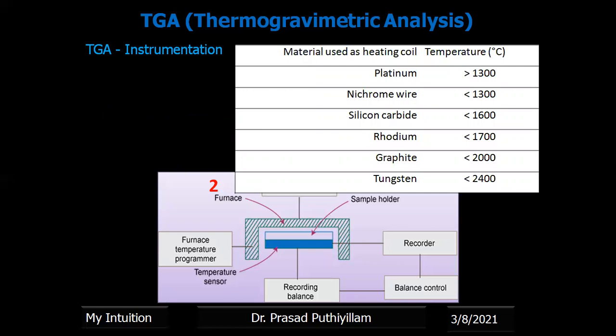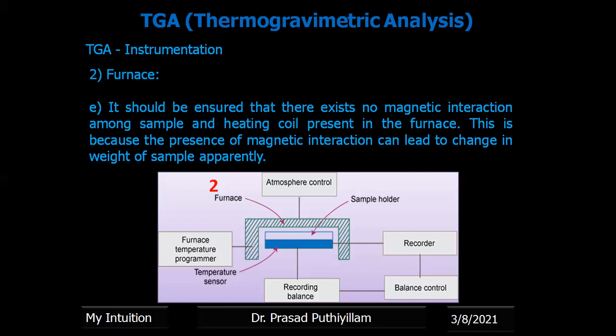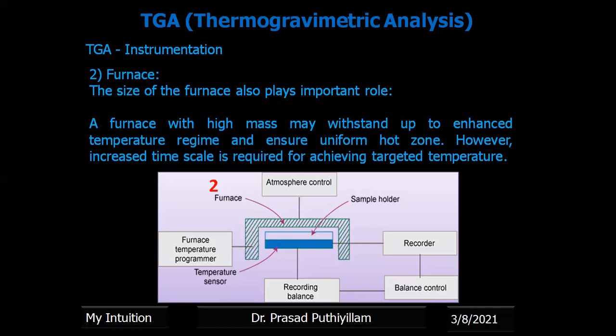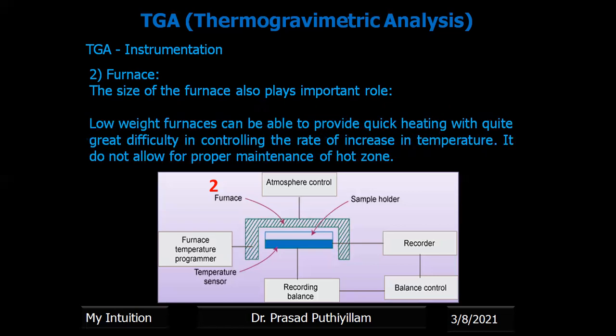Tungsten is used when the temperature conditions required are above 2400 degrees Celsius. The heating coil used should not create any magnetic field, as a magnetic field will affect the change in mass of the sample. The size of the furnace also plays an important role. A furnace with high mass will ensure a uniform hot zone but takes more time to reach the required temperature. Whereas low-weight furnaces result in quick heating but difficulty in controlling the rate of temperature increase.